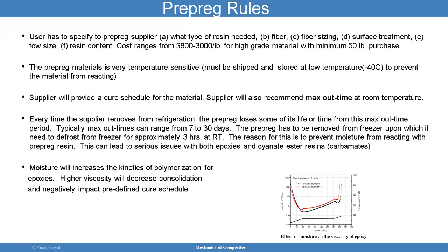The reason for this is to prevent moisture from reacting with the prepreg resin. Like I said, this can lead to serious issues with both epoxies and cyanate ester resins. And it needs to be considered in your application. So make sure you're not making an error in that arena. Moisture will increase the kinetics of polymerization for epoxies. And you're also going to have higher viscosity, which will decrease consolidation and negatively impact the predefined cure schedule. So again, you're going to have some issues that need to be considered. And you can see here the effects of moisture on the viscosity of the epoxy. On the y-axis, I have the viscosity. On the x-axis, I have time. And so definitely there is an effect that's going to be due to the effects of moisture. And so that needs to be considered in your assessments.